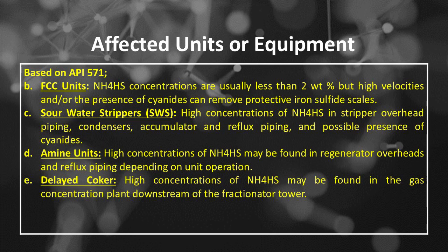Ammonium bisulfide corrosion or alkaline sour water affected units or equipment based on API 571. Number B, FCC units. NH4HS concentrations are usually less than 2 wt%, but high velocities and/or the presence of cyanides can remove protective iron sulfide scales.